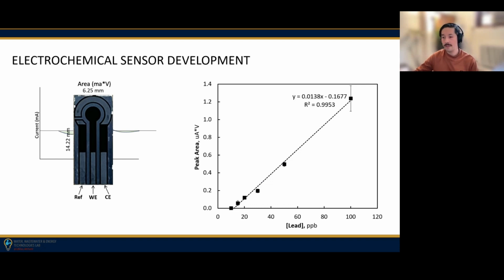So anyone doing chromatography, for example, on the call will know with chromatography or mass spectrometry, we take the area under the curve, and this has some relationship to the concentration of, in this case, lead that was adsorbed to our surface. So we can make this calibration curve where we put known amounts of lead into our water. We run our ASV DPV, which is our anodic stripping voltammetry and differential pulse voltammetry, and we get an area, and we can plot our peak area versus our known lead concentrations. And what we hope to get is this nice linear line whereby our lead concentrations have a linear relationship to our peak area response.